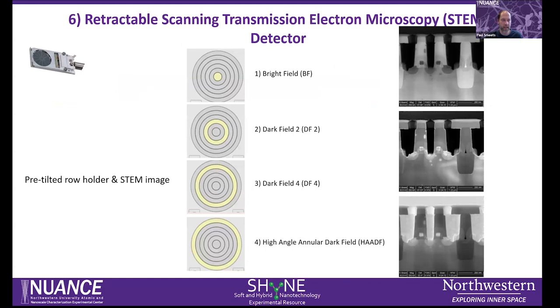We also have a retractable STEM detector present here, which can be used in various modes. We can have bright field, which elucidates more mass contrast in this semiconductor sample, versus high angular dark field mode, where we get more elemental contrast present.